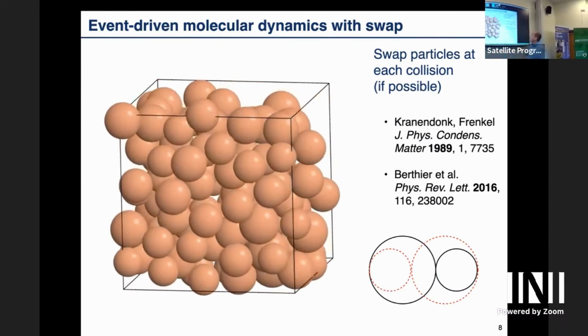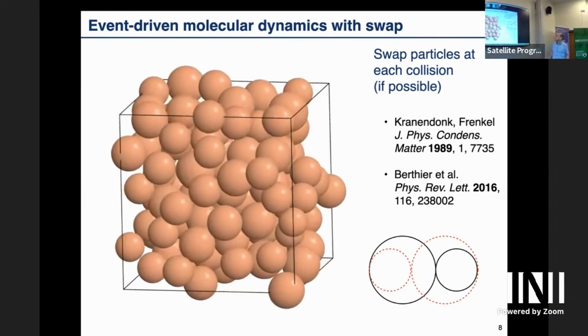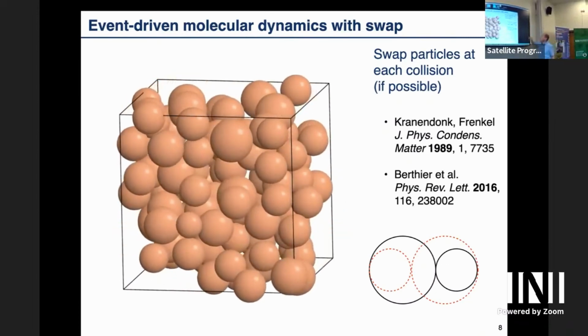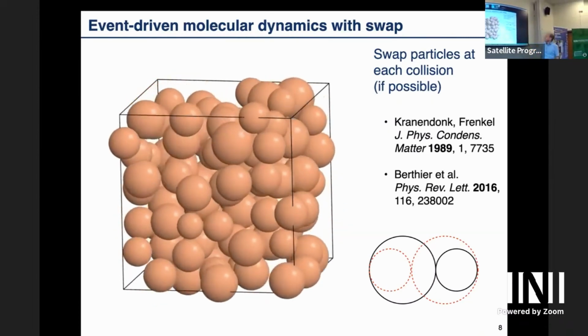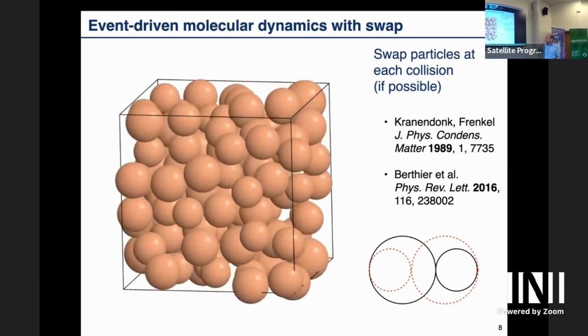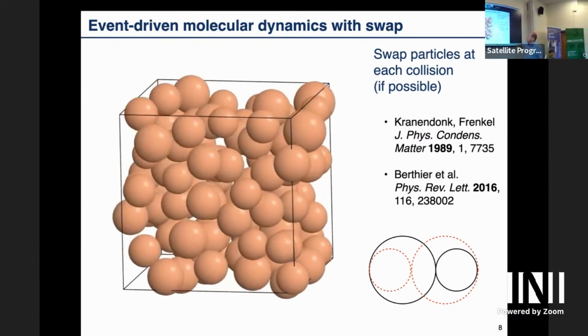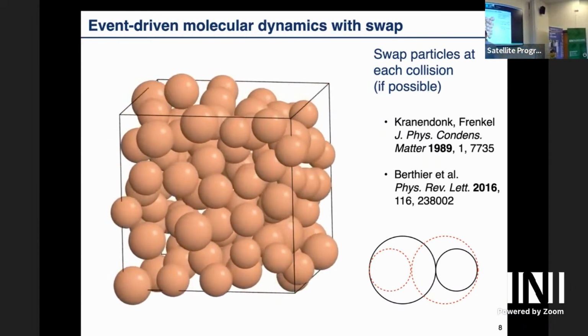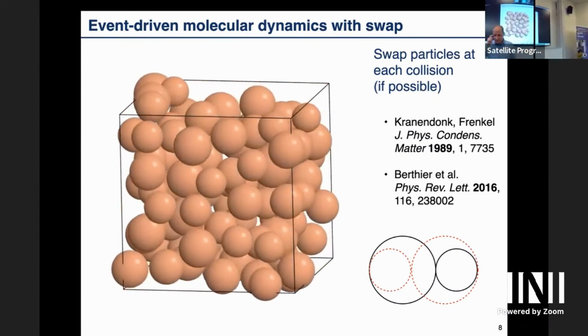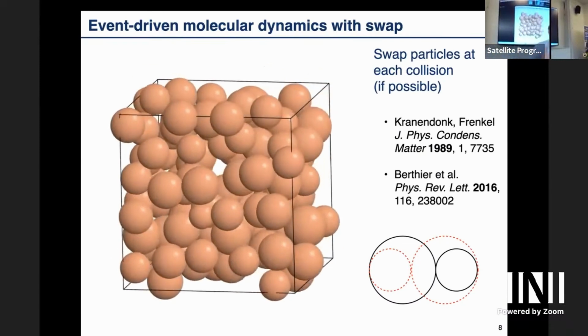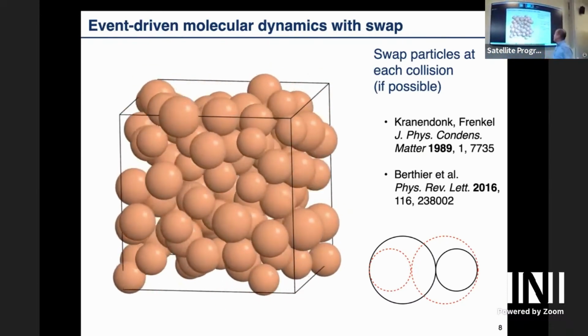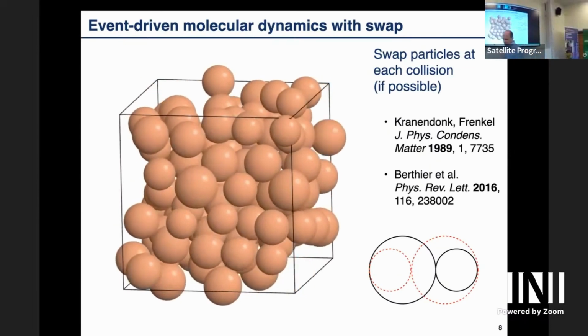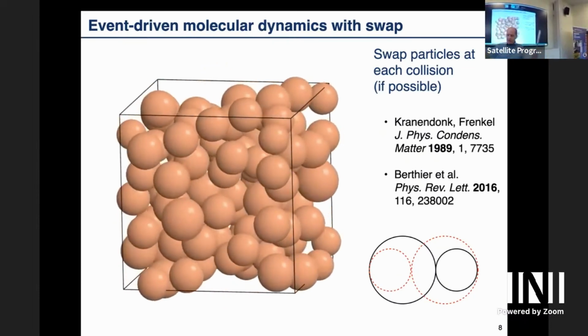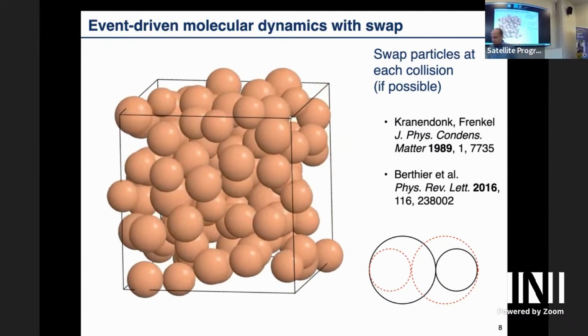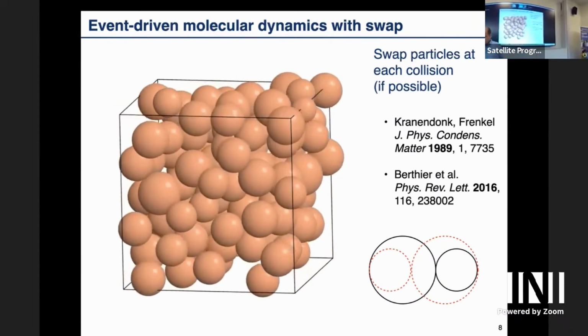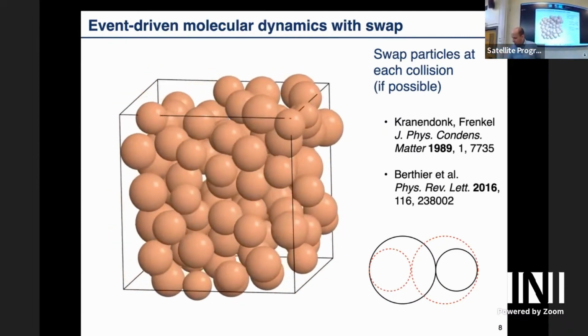This idea of swapping particles is already a little bit old. So the first paper I found was from '89, when Kranendonk and Frenkel, they talked about this idea of swapping particles, and Ludovic Berthier recently has done a lot of work with swapping particles to relax glasses better and to reach timescales that you cannot reach with other methods. And it's a pretty established method. The thing that we added is this idea: when they collide, we swap at that time, and that adds a little bit more performance. And actually, these are super. You can relax systems super fast.